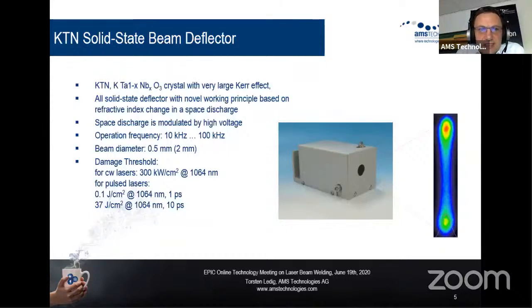The working principle of this device is that this crystal material, KTN, shows a very large Kerr effect, which means that under an electric field, you get a refractive index change in the material, and this electric field can be modulated to get a different space charge in such a crystal. By changing this space charge, you change the refractive index, which finally leads to a deflection of the incoming beam. And this device can be quite fast. It can run at an operation frequency of 10 kilohertz up to 100 kilohertz. The beam diameter is quite small, but there are developments ongoing to increase the beam diameter which can be handled by such a device.